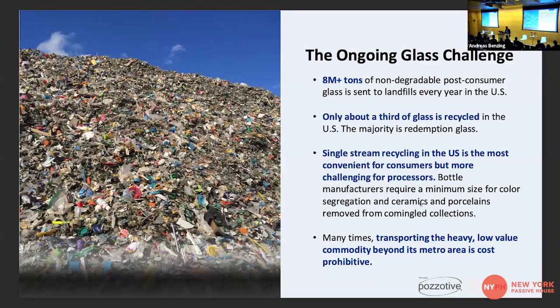So we have to take that pile, basically, that you see here, and that's what we get as our feedstock, and create a feedstock for our Positive or ground glass pozzolan that has a percentage of loss on ignition below 0.5%, as ASTM C1866 prescribes. I was one of the authors; it was spearheaded by Amanda Kaminsky of Lendlease, who was an enormous help with getting that done. So through that standard, we created an understanding on how to process post-consumer glass into a pozzolan, and creating consistency and quality in the product. So that was a big changing point. And that was published in one of the only good things that came out of 2020, in April of 2020.